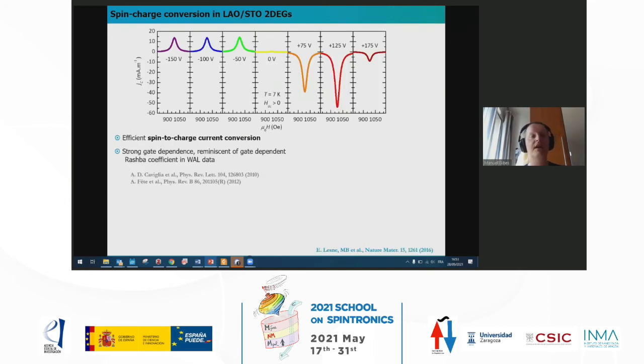And what was very striking in these results is, first, the effect is very large in these 2DEGs, very, very large, and we'll come to that. But also when we apply gate voltage, so basically we have a back gate and we accumulate or deplete electrons. Basically, we put the Fermi level at different positions in the band structure, and we'll also come back to that. We see that the amplitude, even the sign of the effect changes. And this is really a very unique feature of these STO 2DEGs.